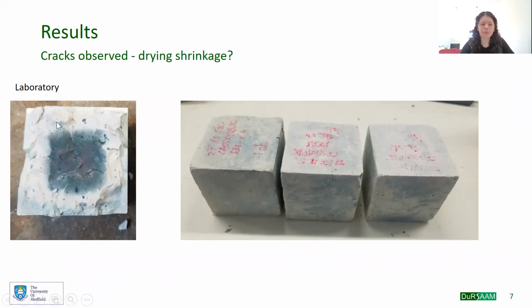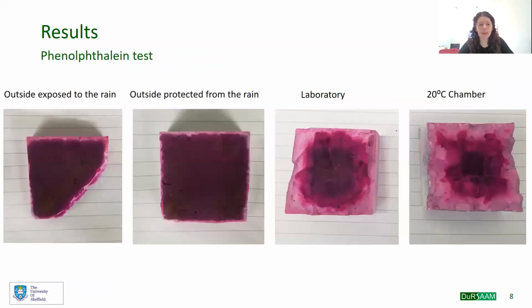We can assume, but we're not sure, that maybe the carbonation front is equal to the change of color front, to the oxidation front, because the CO2 can go as far as oxygen. But after doing this phenolphthalein test, we can see that actually the carbonation front doesn't look like the oxidation front.